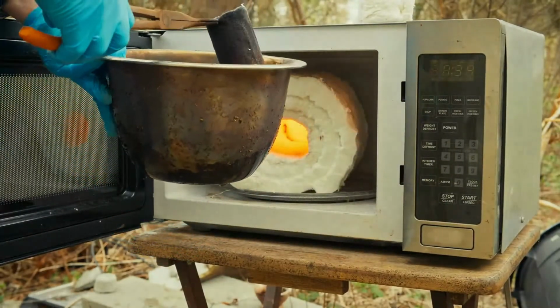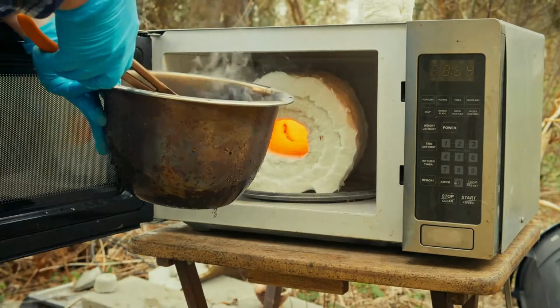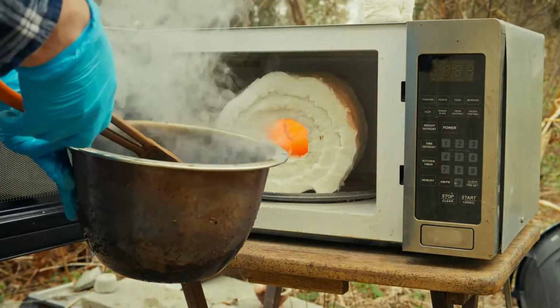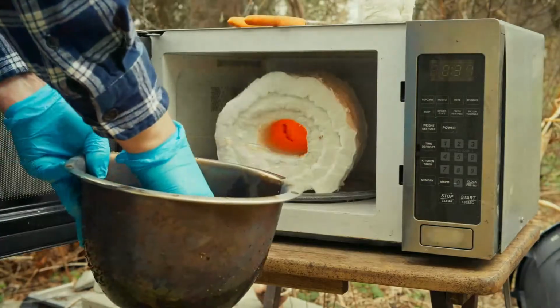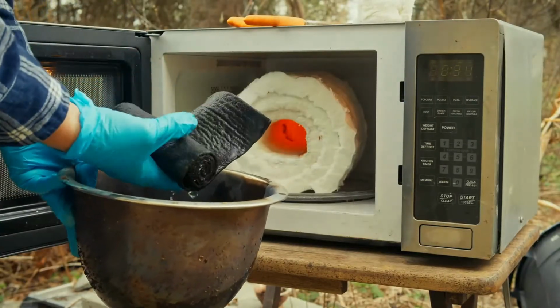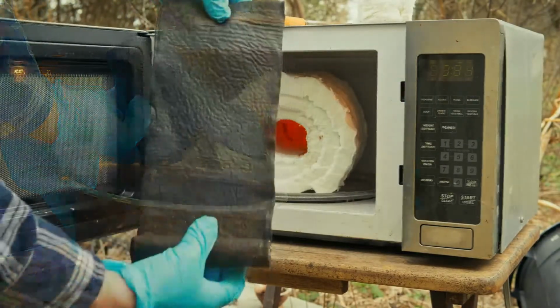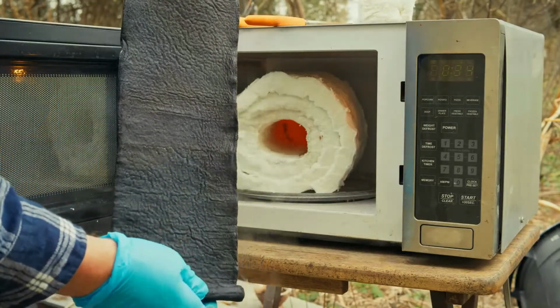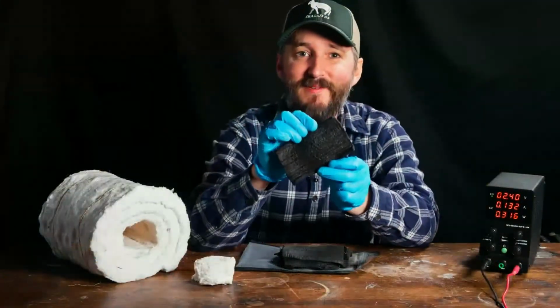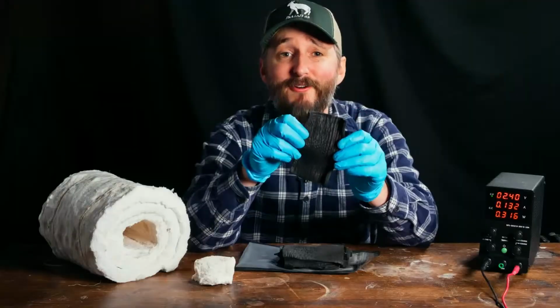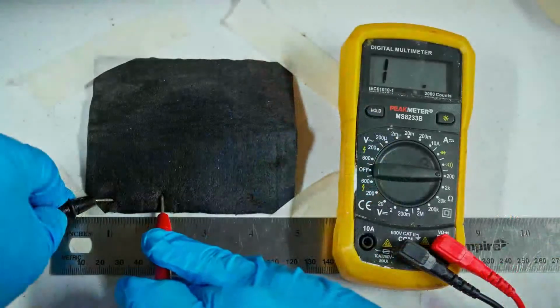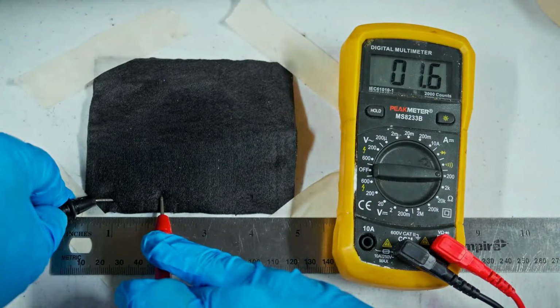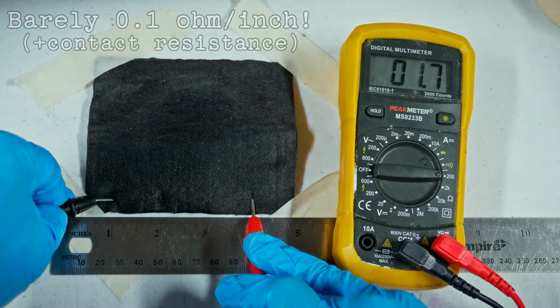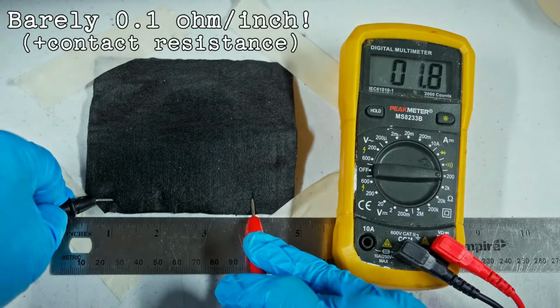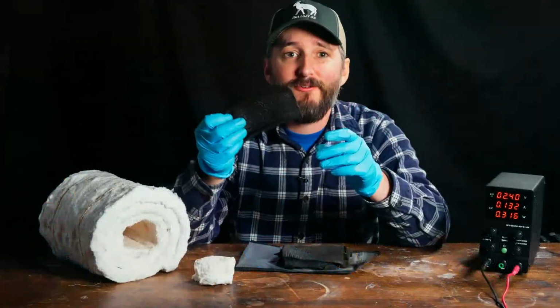This does 2 things. It cools the carbon down before it reacts too much with the air, and it also stops the felt from throwing off those fiberglass-like needles as dust. Once it's made, I always keep this wet so that dust is no longer an issue. And this is the best electrode material you are ever likely to see. It has extremely low electrical resistance, extremely high surface area, and is very resistant to the strongest chemical solutions. With this for our electrodes, let's turn back to our battery project.